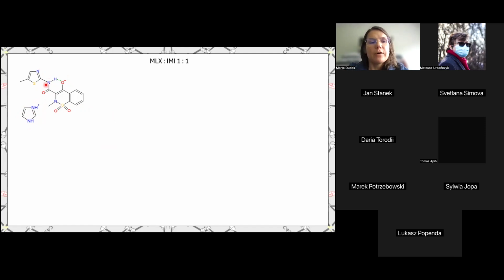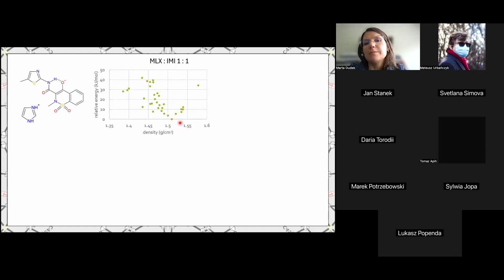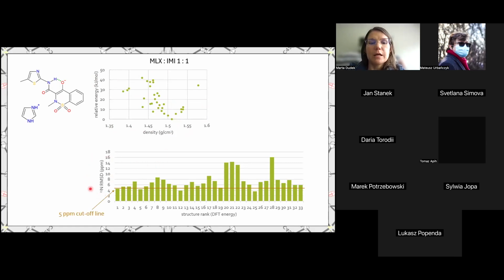So because we did not have a crystal solution for this crystal, we decided to do CSP calculations. So this is a CSP plot of the relative energy of the lowest energy structures we got from CSP calculations against density. And you see that there is this one nice minimum energy structure. And when we calculated the nitrogen 15 RMSDs for all of those structures, you can see that there are few of the structures that fall below the 5 in this case, ppm cutoff line. Among them, there is this first structure, but there are also 3 other structures.